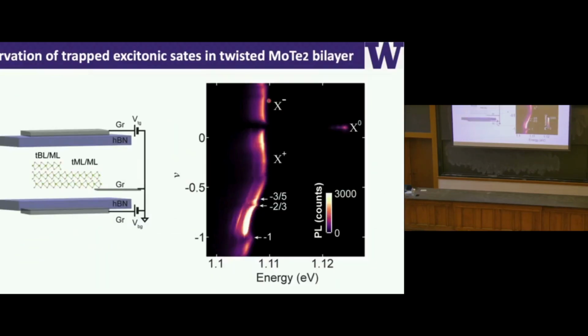So let me show you our experiment. What we have here are samples which are kind of unique. In addition to a twisted monolayer on monolayer, which is a twisted bilayer, I have a twisted monolayer on top of a natural bilayer. So there's an interface formed here. What we found is that this interface is interesting and can trap these fractional charges.